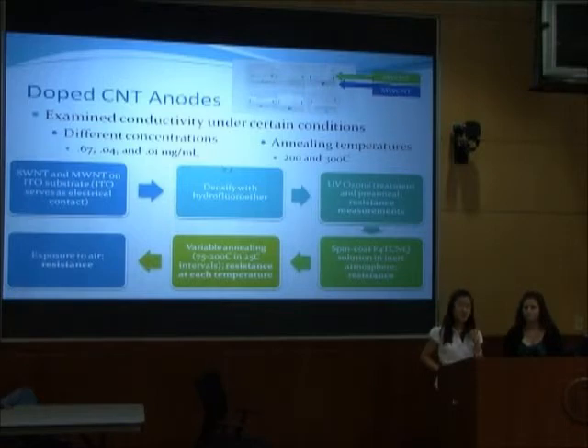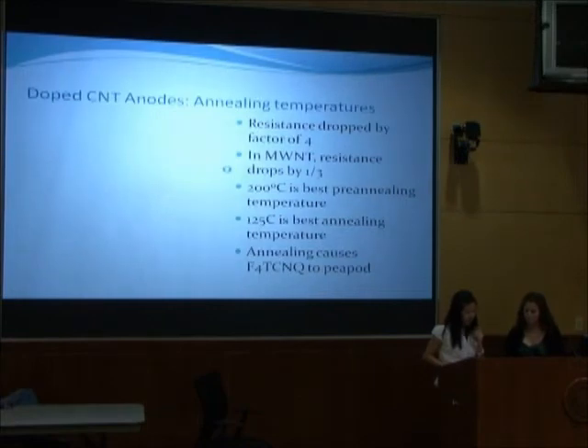After that, we spun coat the F4TCNQ dopant solution in an inert atmosphere. And then we annealed the doped carbon nanotubes from 75 to 200 degrees Celsius in 25-degree intervals, and we took the resistance at each temperature. Finally, for our lifetime studies, we exposed the carbon nanotubes to air and measured their resistance. So here are some of the results for our nanotubes.